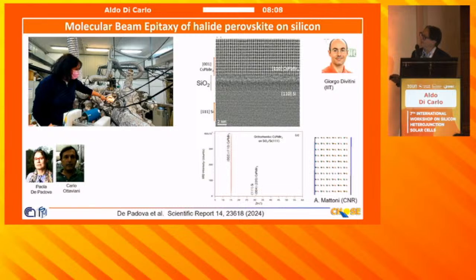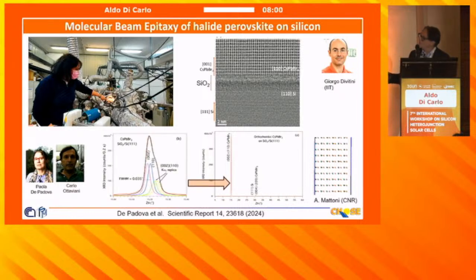And then I want to show you the diffractogram, the XRD plot. You can see the XRD plot of this perovskite is very narrow. If we zoom in, the width of this line after the convolution is 0.035 degree. So it's really a crystal structure, an epitaxial layer grown on the silicon 111. So it is possible to create epitaxial perovskite, and I believe this will help a lot, both from a physical point of view and to have better devices. And this is a model.